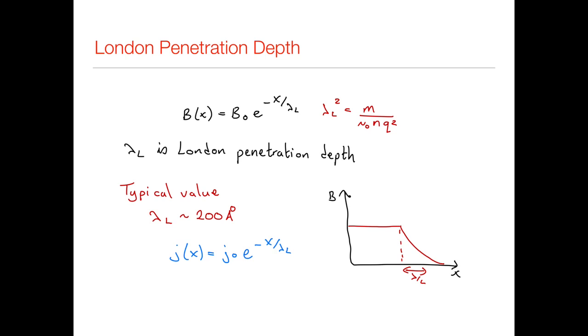There's just one thing I forgot to mention. So we came up with an expression here for the London penetration depth. Okay, and that depends on a bunch of constants, m, mu naught, and q that we can't change. But what about n? So n is the superconducting density. What would happen as we approach the transition temperature from below? Well, n is going to decrease. As we reach Tc itself, n will go to 0.